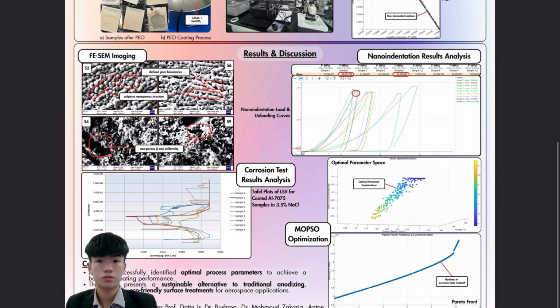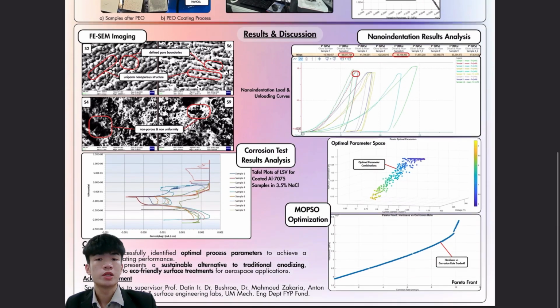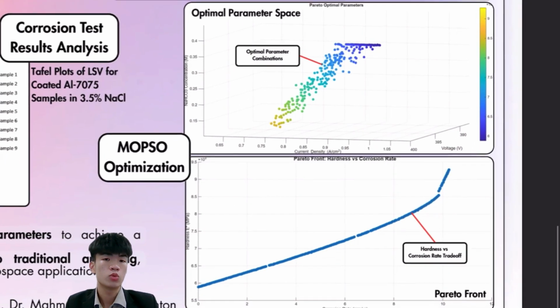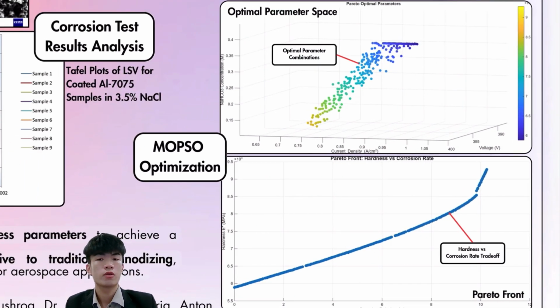performing coatings. Next, all the experimental data, no matter ideal or non-ideal, were fed into the MOPSO algorithm for carrying out the last phase of optimization. The two objective functions here in the algorithm were to maximize hardness and minimize corrosion rate. Using regression models that were built from the Taguchi experimental data, MOPSO produced a Pareto front, which is shown here, and this figure showcased the trade-off relationship between the two objectives. The optimization revealed that increasing hardness, indeed, as expected, often leads to higher corrosion rates and vice versa.